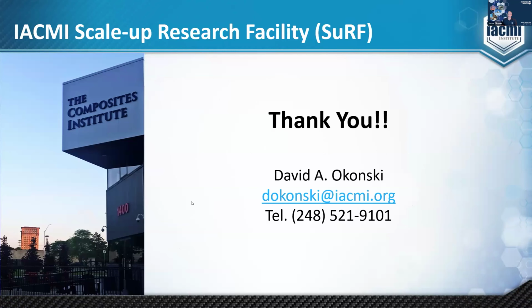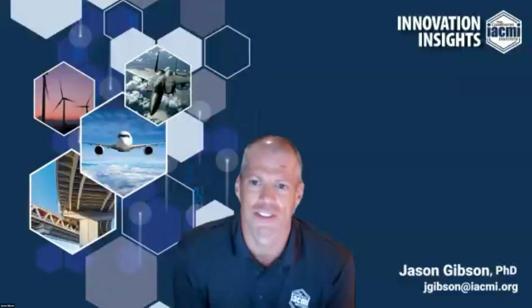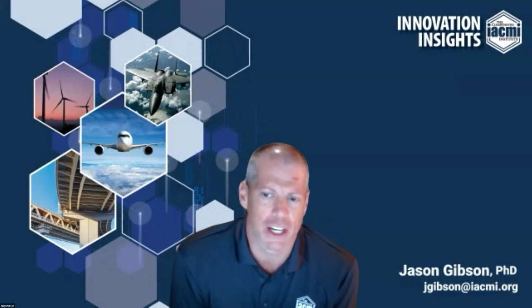Thanks, Dave. We got a number of questions here, and hopefully we can knock them out in the next 3 minutes. I'll start with: how accurately can you control the thickness with the water assist? The thickness was pretty accurate. Once you were at cycle and established a good equilibrium with your tool temperature and your melt temperature, your part thickness was very consistent. I can provide measurement results after the presentation, but it was very consistent.